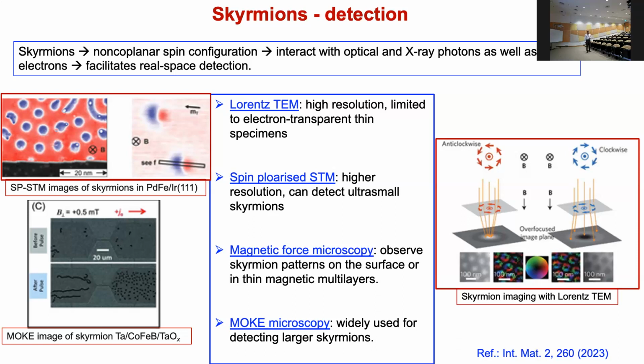In particular, there have been many recent advances in these technologies, and there are 4 primary probes to detect real space configuration of skyrmions. This includes Lorentz TEM, although they are limited to electron transparent thin film specimens. Spin polarized STM is another very powerful method that can detect ultra small skyrmions. Then we have magnetic force microscopy and also MOKE microscopy based on the magneto-optical Kerr effect, which are primarily used for large-scale skyrmions.